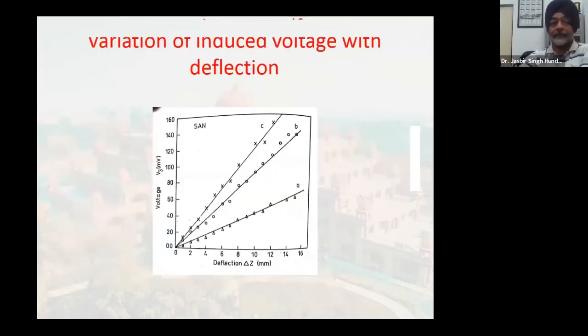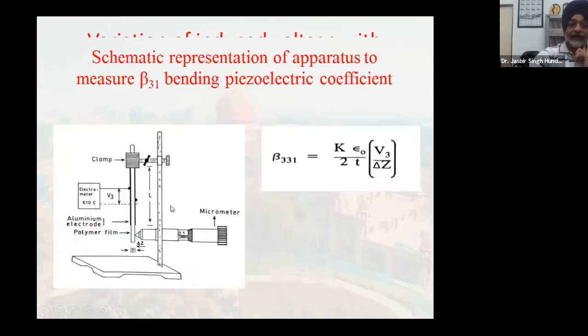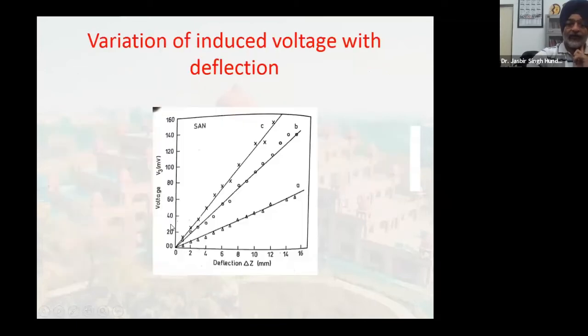Okay, now this is the case in styrene acrylonitrile. And now the first curve is for unpoled films. Look here, even unpoled films do have some kind of bending piezoelectricity. Now this is poled films, but not stretched. These are stretched and poled films. So we find that the voltage developed by bending was maximum for the stretched and corona poled films. We have three curves here: for unpoled films, for poled but unstretched films, and C, stretched and corona poled films. So best results were obtained in the stretched and corona poled films.